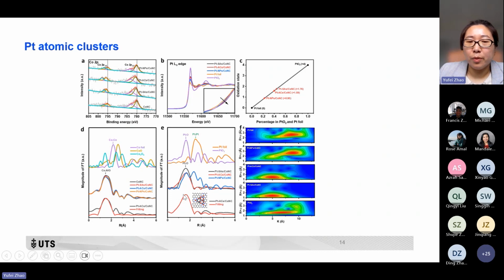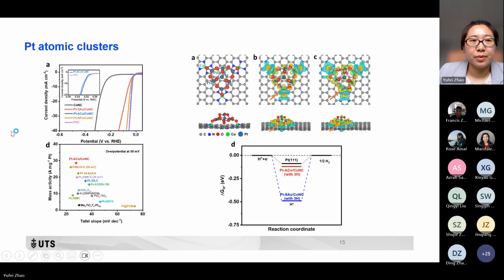For the platinum, we have done the simulation to achieve the atomic structure. And for the performance, we can see here it shows quite high performance for the HER in acidic condition, and it's slightly better compared to the commercial platinum. But the mass activity is much higher than the commercial platinum, because the commercial platinum has a much higher loading of platinum on carbon, but for ours, the loading is quite low. So for mass activity, it shows very good performance.